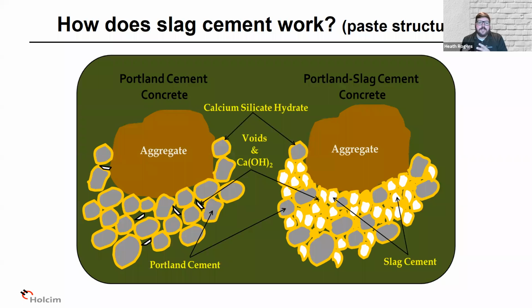Slag cement has the same mechanism. It grows these calcium silicate hydrate fingers, and there's also some synergies with the Portland that is available. So you get a nice, dense, strong paste structure when using slag cement.